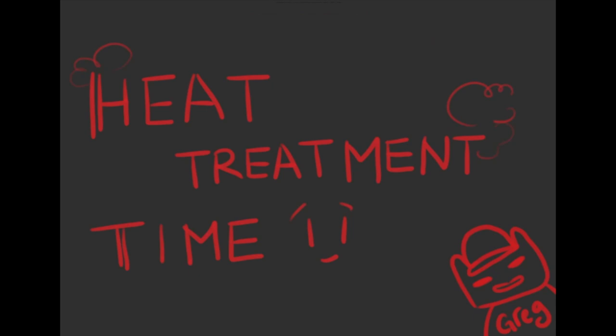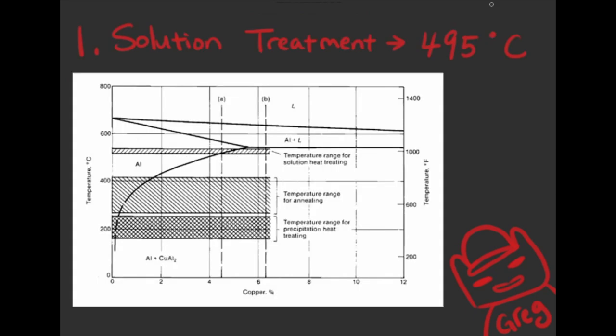Precipitation hardening was chosen as the main form of heat treatment, because it can change the material property of a metal, such as strength, without significant changes to its density. As well, the process gives us lots of control over exactly how we want these properties to change. We first start off with solution treatment. In this step, we homogenize the Aluminum alloy into one alpha phase at 495 degrees Celsius, seen from the phase diagram, to prepare the material for quenching.